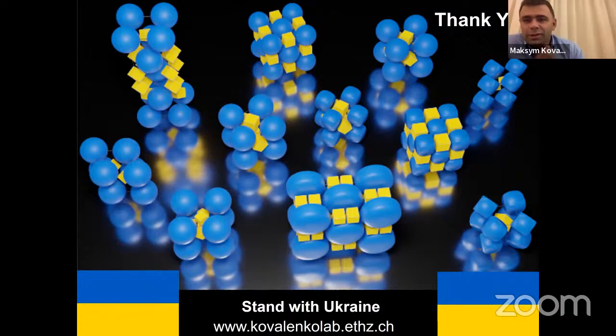Now, Serhat writes, I tried to use them as a scintillator for X-rays. My answer to that is that I hope you had good results, but my doubt about scintillators generally, based on perovskite, is that if your goal is to make a scintillator with good light yield, you need to have a thick absorber layer. And with perovskites, which have very small Stokes shift between the emission and absorption bands, there is a lot of reabsorption. So I'm a bit skeptical for scintillator applications of them in those applications where the light yield is the key.